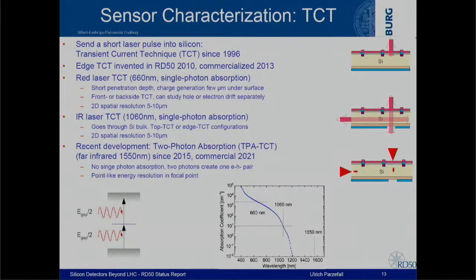Transient current technique is a method where a short laser pulse is injected into the silicon, typically starting with a red laser that can be injected from the top or bottom. Looking at the absorption coefficient as a function of wavelength, this has a very high absorption coefficient, so the red laser is absorbed pretty much at the surface, but gives reasonable 2D spatial resolution.